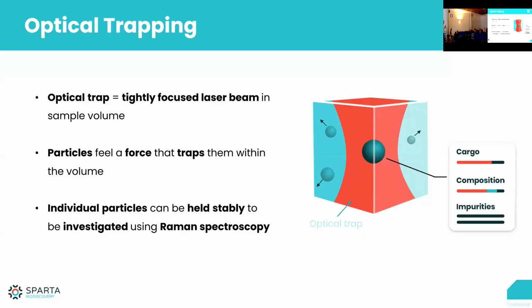So basically what we do is we have all these particles diffusing around with Brownian motion, and we have this very tight laser spot. And if a particle gets close enough, it stops the Brownian motion of the particle in that focal point. So we can have that particle kept still inside that point. And at that exact point where we have that laser focus, we generate the most Raman signal because it's the focus point of the laser. And that's where we can then collect the light off from that particle.